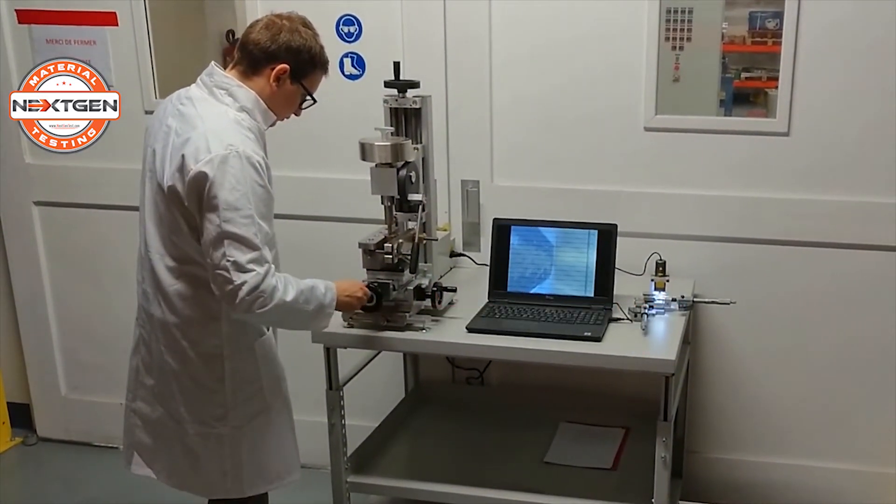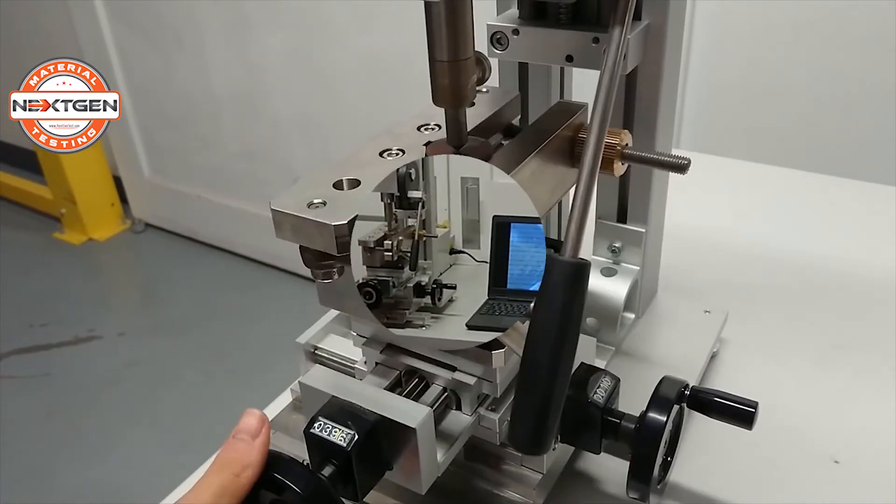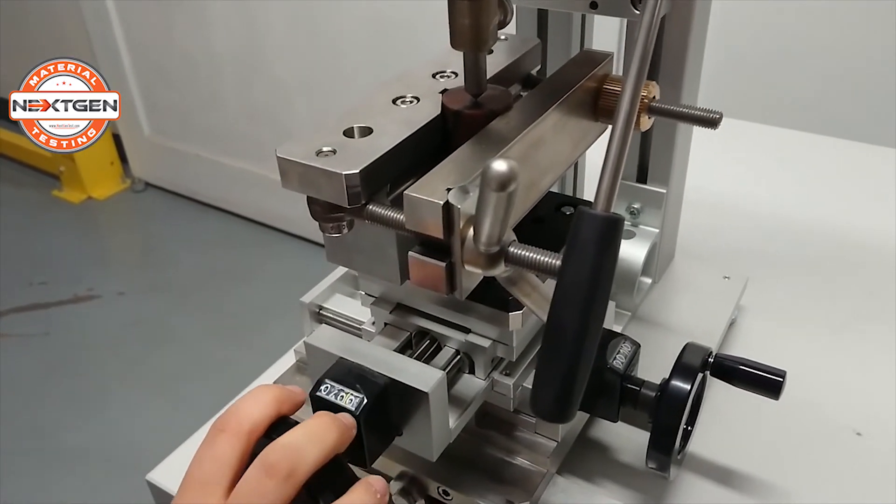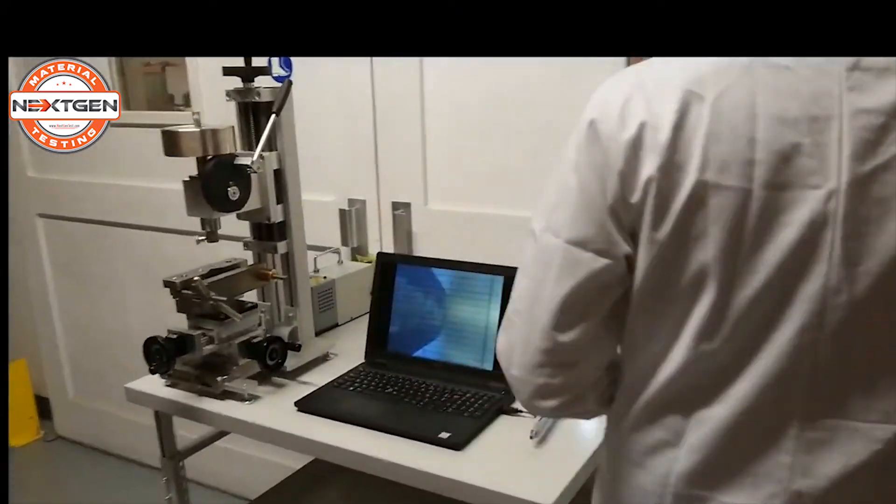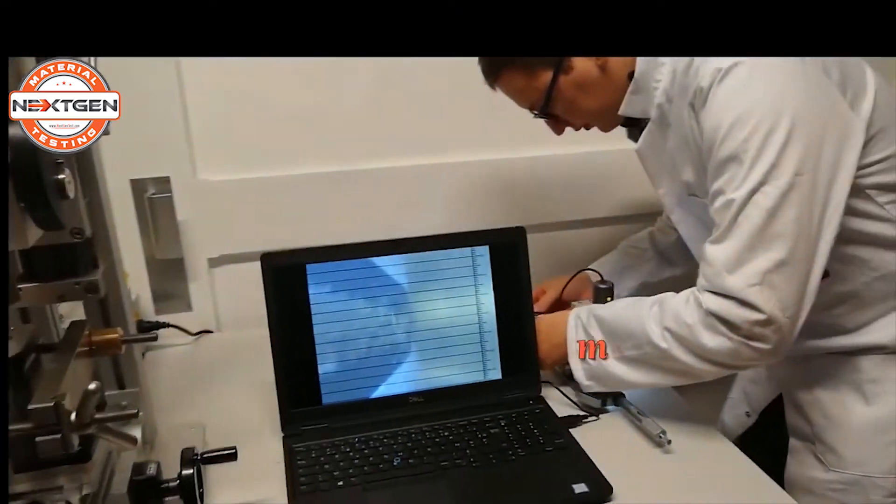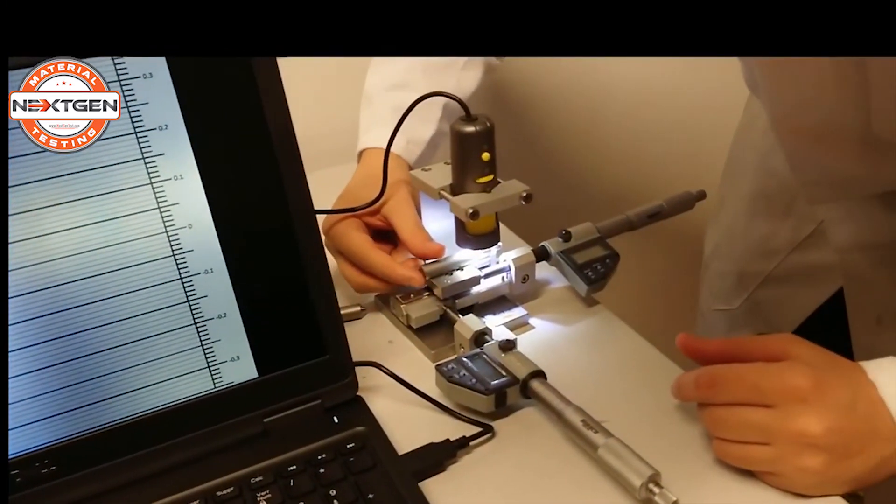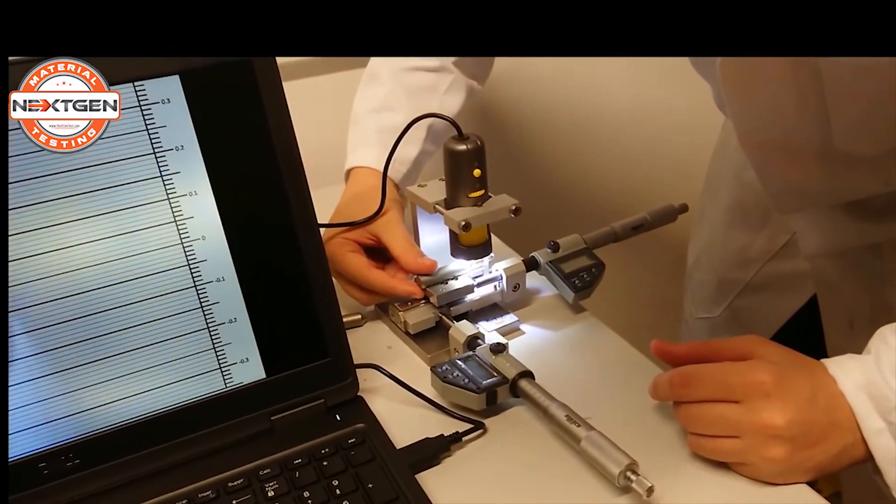The movement of the axis produces a reproducible 10 mm long stripe. The width of the wear flatness is measured on the stylus tip surface using a digital microscope, and the Scratch Abrasivity Index can then be calculated.